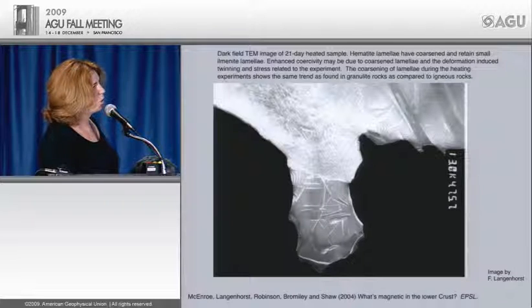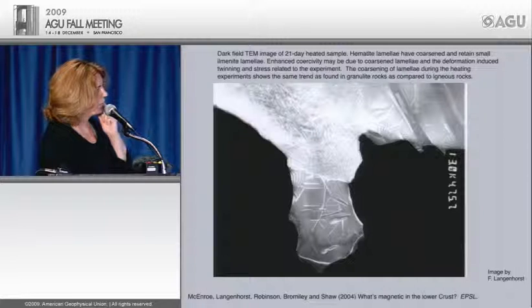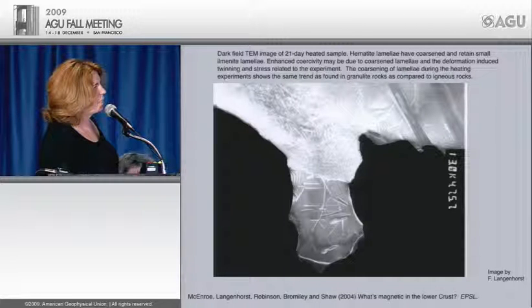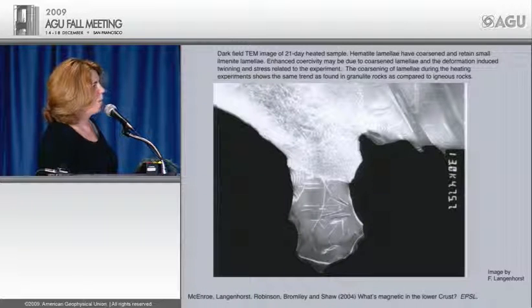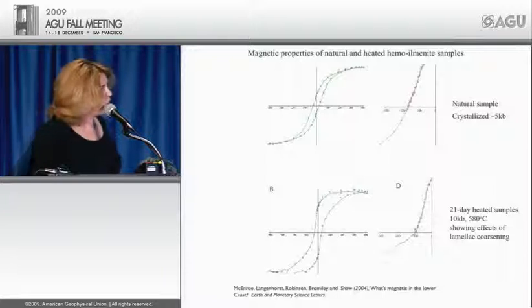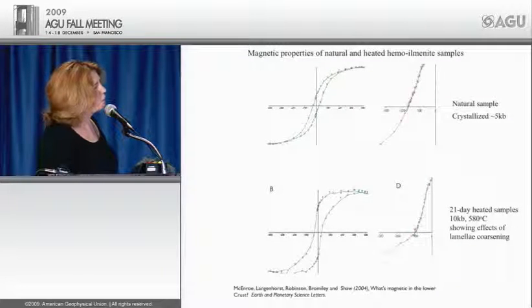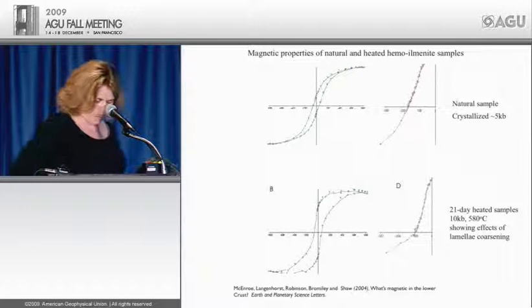We also did a lot of work with the exsolution lamellae. It was very clear the hematite lamellae had ilmenite lamellae in them, but the ilmenite itself was losing some hematite. This is based on the chemistry. We did chemistry both at the microprobe level and the TEM. We also induced a lot of twin deformation in the samples. And the twin deformation probably is what's responsible for some of the change in coercivity that we have from the ilmenite sample to the sample that was recovered. But also, we are having some coarsening of hematite.